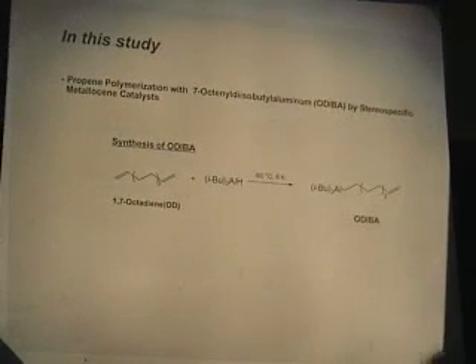A new approach to the functionalization of polypropylene is direct polymerization with a boron-containing monomer. This method focuses on the stability of the boron components to the active site of the catalyst and the versatility of functionalization. As described above, it is still difficult to produce well-defined functionalized polypropylene due to the simultaneous control of copolymerizability and stereospecificity.